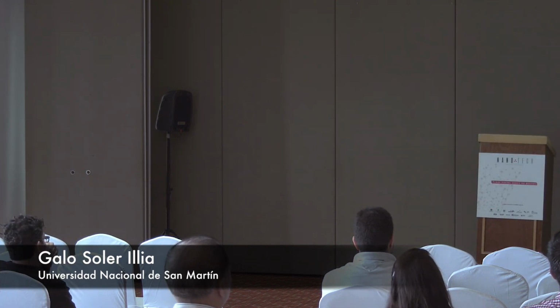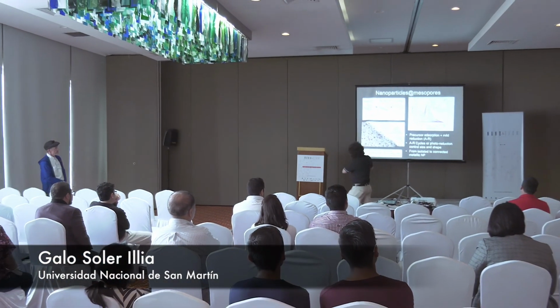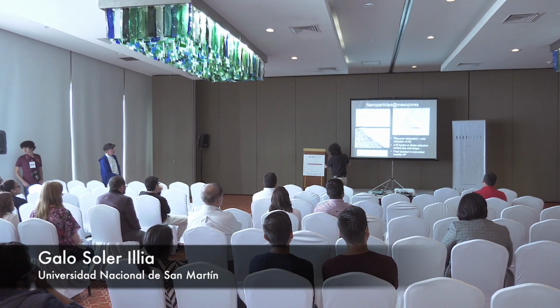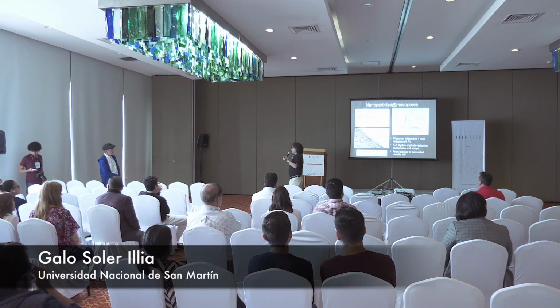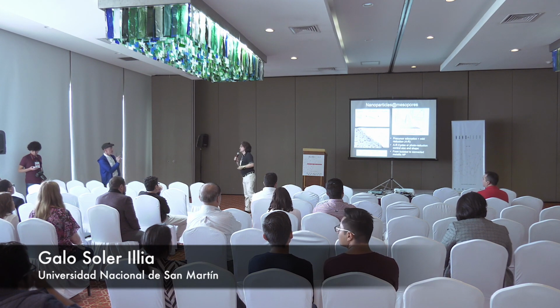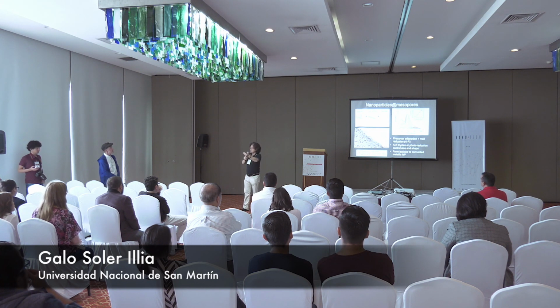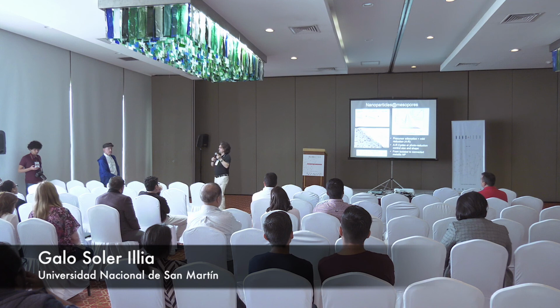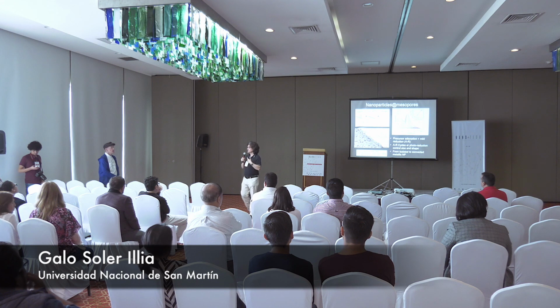what we observe here is that when we produce nanoparticles inside this, like a ship in a bottle, we first produce small particles, and then we see a shift in this peak, and we modeled this system, and what's happening is that we begin always to create small particles, but then to populate our pores. And whenever the distances become close, you have a change in the plasmon due to the proximity of a second particle. We use that as a measurement of the pore filling and the average distance between the particles. There is an effect, a collaborative effect, in some regimes. Thank you.